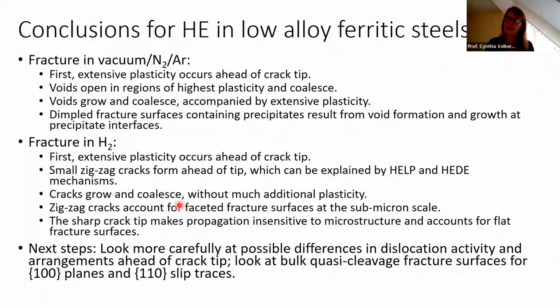And the point I want to bring up is that in both of these specimens, before the crack propagates, there's significant thinning. And so far, we have not seen a difference in the effect of hydrogen in that initial plasticity ahead of the crack tip. That's something we're going to look at very carefully, because that's basically the evidence for a HELP mechanism, which would argue that the plasticity should be different in the two cases. So far, we have not seen evidence for that. So that's something we need to look at more carefully.